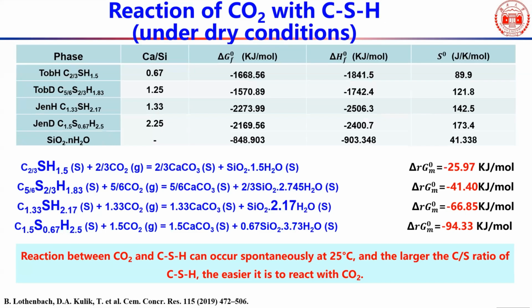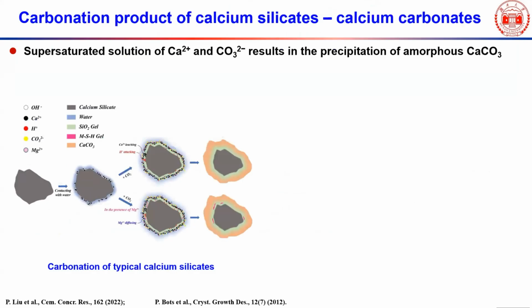And so even all those calcium silicate hydrates, you can see their free Gibbs energy is almost between minus 26 and almost minus 95 kilojoule per mole, and they're also very negative. But on the other hand, in the dry condition, they also carbonate very, very slowly. So this means moisture or a certain amount of water is very important, or even critical, for fast carbonation or carbon mineralization.